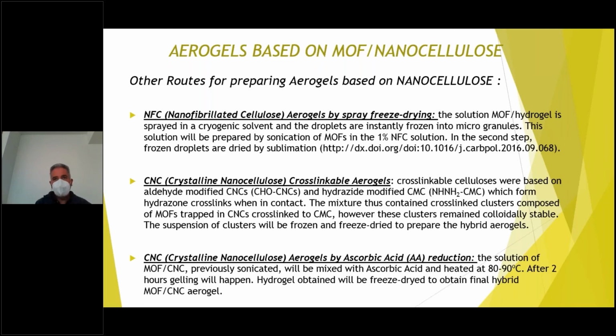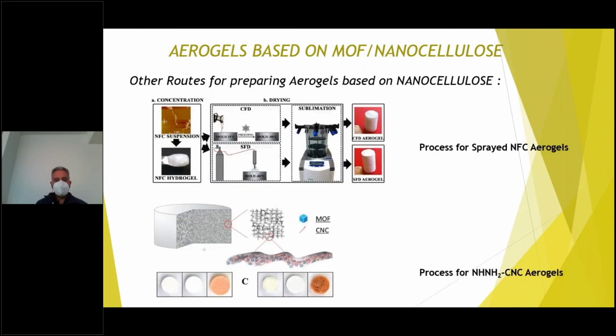crystals, making the hydrogel structure, the polymeric structure, and then by the drying process that I have explained before, we have the final cross-linked aerogel. And finally, another process that we can explore is to make crystalline nanocellulose aerogels by ascorbic acid reduction. This process is very well known for making, for example, graphene aerogels, carbon nanotube aerogels, and activated carbon aerogels, but it has been explored for nanocellulose. Visually, we can see that we can make different processes to prepare this aerogel based on nanocellulose.